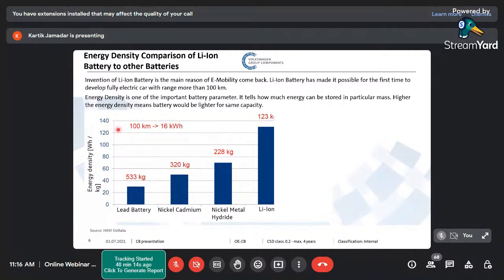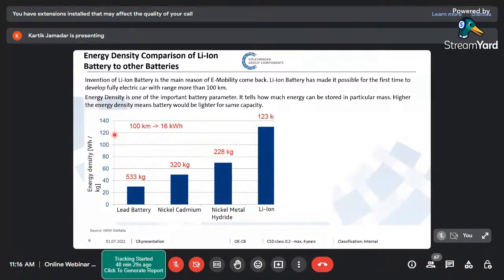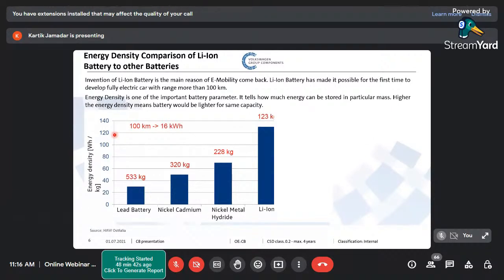And here the range is 120 watt hour per kilogram. If you have seen the latest Tesla cars, they give 280 watt hour per kilogram. So we have already given more than double that energy. LG and CATL, the big battery manufacturers, have already said they would go up to 300 watt hour per kilogram in the next generation of lithium ion batteries. If we reach that, which is very much possible in the next 2 or 3 years, we would get much more mileage for the same weight.